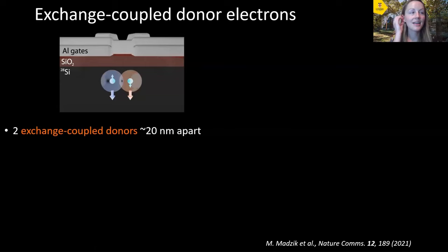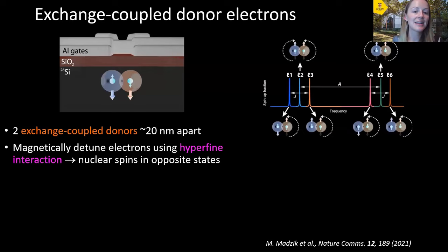So in this particular device, we had two phosphorus donors that were implanted about 20 nanometers apart. And at this distance, each of the donor nuclei binds its own donor electron. And these two electrons are exchange coupled with each other. So we first magnetically detune these electrons using the hyperfine interaction by preparing the nuclear spins into opposite states. So either spin up, spin down, or spin down, spin up. And so if we just focus on the electron spin resonance transitions highlighted in the bottom row, then we have 4 different electron spin resonance frequencies for the target electron shown in brown that depends on the state of the nuclei and whether the control electron shown in blue is a spin up or a spin down.